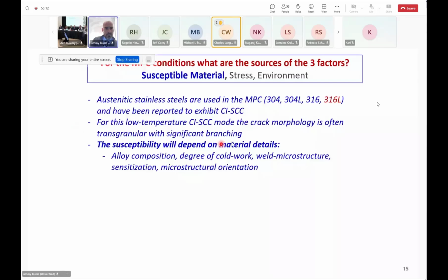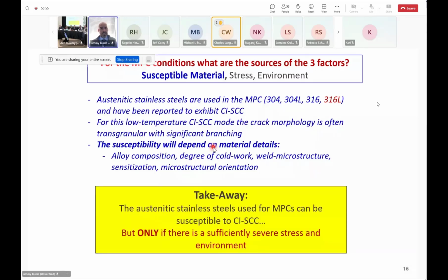Now, remember how I talked about how the extent of susceptibility can depend on the details. Different materials can crack at different rates, and that susceptibility depends on the details of the material composition, the extent of what we call cold work, and that's the amount of dislocation or plasticity put into it that kind of correlates to the strength of the material. It can depend on the weld microstructure, a phenomenon called sensitization, and microstructural orientation. So there are details of the material that impact how susceptible it's going to be to this damage mode. The thing I want you to take away from this discussion, to summarize the three factors: susceptible material, stress, and environment. Talking about susceptible material, these stainless steels can be susceptible to CISCC. But as I said, only if there's sufficiently severe stress and environment.